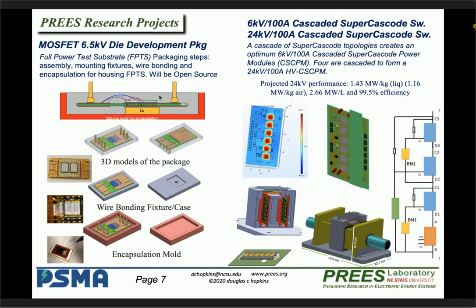And we've chosen the series approach because we can get much better higher power thermal management, et cetera, from the lower voltage, much higher current die at much higher speeds. You know, we're reporting 45 nanosecond switching on our 6.5 kV 200 amp module, DVC. And we should be able to go faster on this because of the organics.